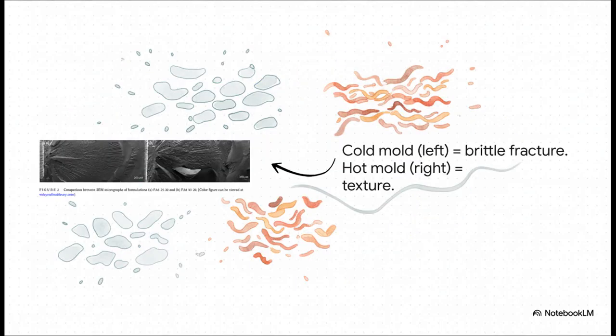And you don't even have to trust the chart. You can literally see the difference under a microscope. On the left, you've got the sample from the cold mold. See how smooth that break is? That's a classic sign of a brittle fracture. Now look at the right. The sample from the hot mold is all rough and torn. That texture tells you the material really fought back and absorbed a lot more energy before it finally broke. That's toughness you can see.